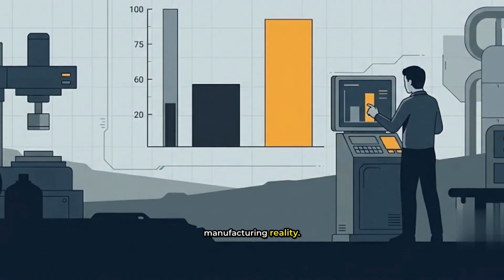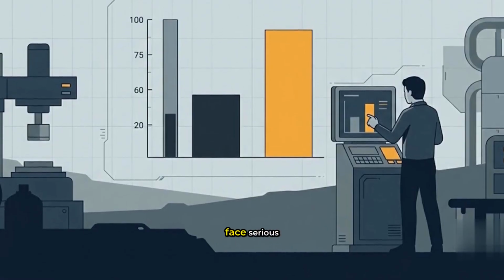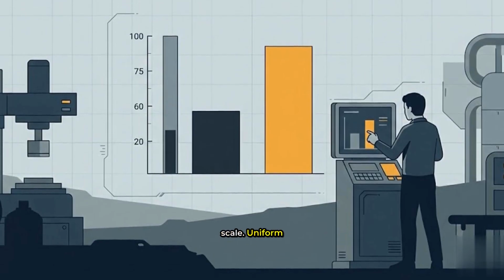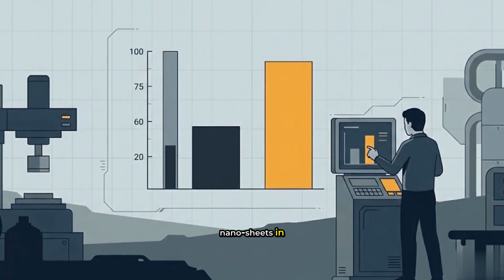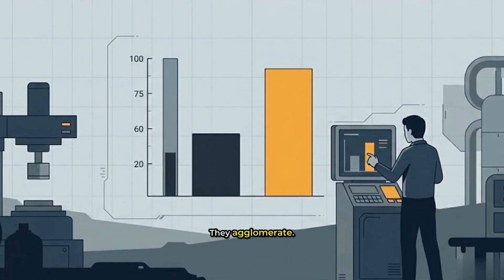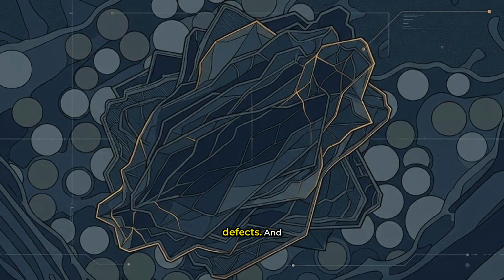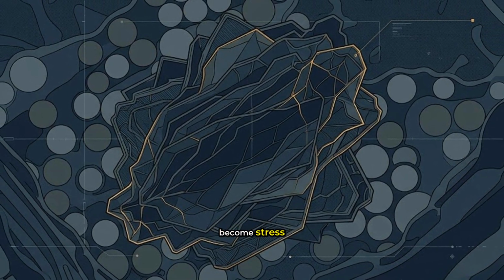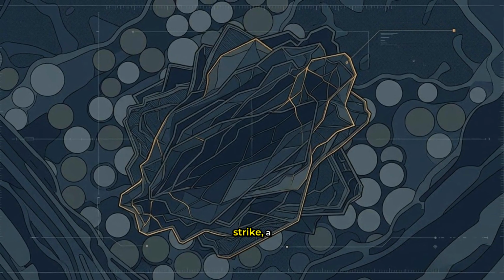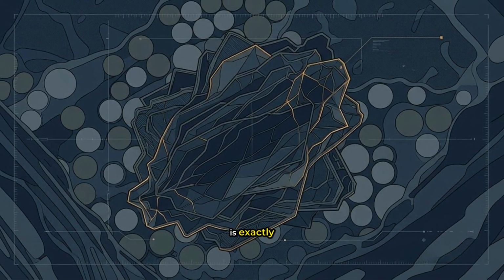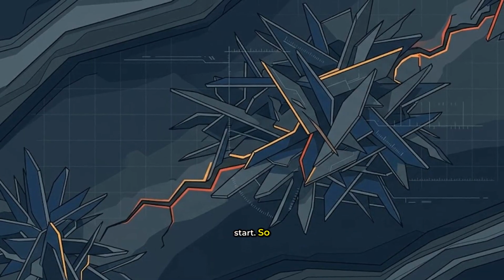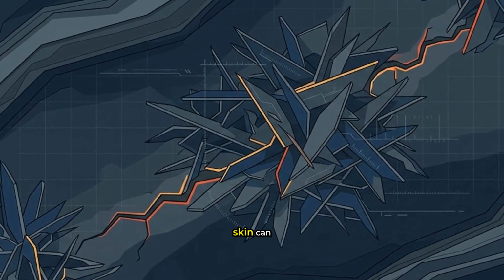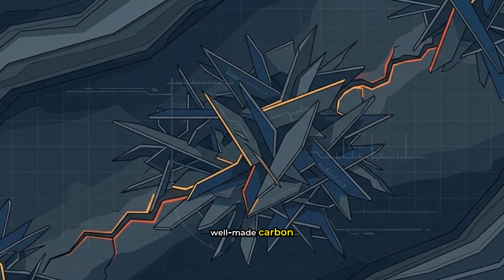Now consider the manufacturing reality. Graphene composites face serious challenges at scale. Uniform dispersion of nano sheets in the epoxy is difficult. They agglomerate. They create defects. And those defects become stress concentrators. In a bird strike, a stress concentrator is exactly where a crack will start. So a poorly manufactured graphene skin can be worse than a well-made carbon fiber one.